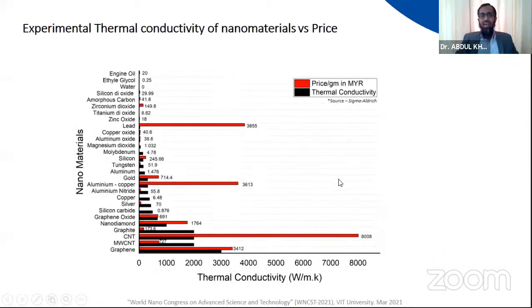When we combine them, for example, graphene has very, very high conductivity. We have other carbon-based materials, CNT, multi-wall CNT, and so on. When we combine such materials with, for example, water, sorry, the value is wrong. Water has 0.6 watts per meter Kelvin. So you can imagine 0.6 watts per meter Kelvin combined with such a high conductivity, the combined effective thermal conductivity will be much, much higher.